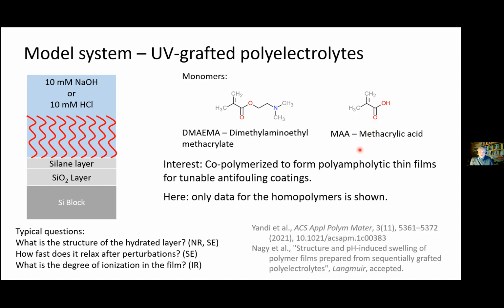The data I will show will not be from a copolymerized system, but just the homopolymers. And the geometry of the sample is this. We have a silicon block, an oxide layer, a silane layer to couple the polymer to the oxide, and then the polymer. And this will be measured at low and high pH.